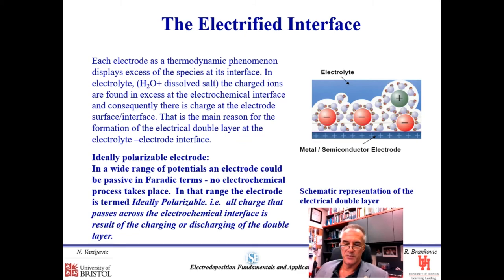This is due to the spillover of electron functions from the metal, which faces the charged particles in the electrolyte that mimic this charge with opposite ion charge. This means that we face a certain capacitance phenomenon due to the presence of charged species facing the electron cloud on the side of the electrode surface. That charging has nothing to do with electron transfer, and those electrodes that can have only charging and discharging in the double layer are called ideally polarizable electrodes in a certain potential regime.